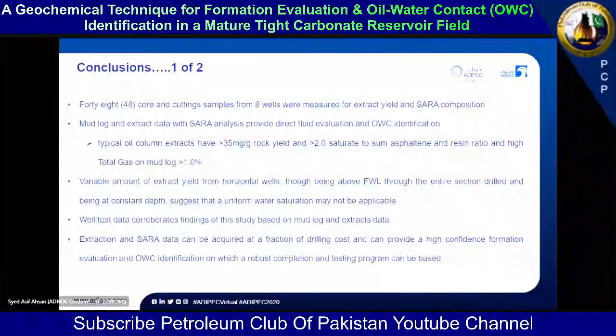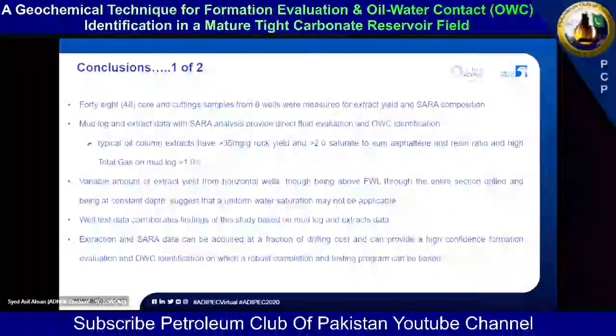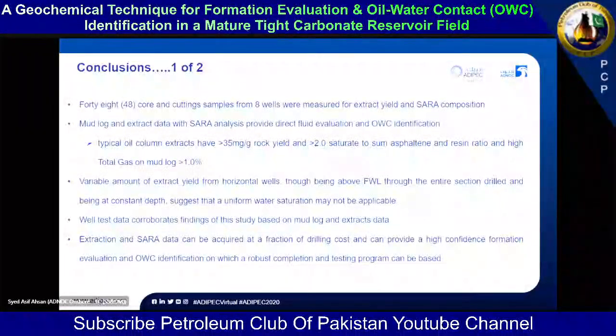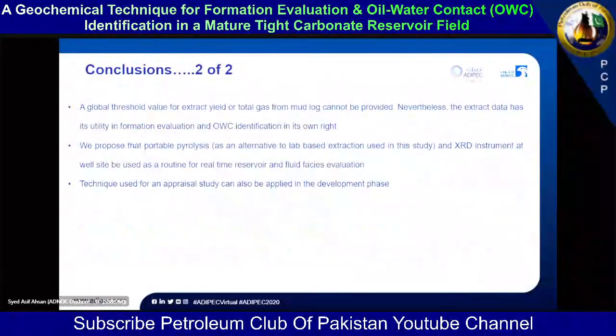Extraction and SARA data and well test data corroborate the findings of this study based on mud log and extract data. So we have plenty of test data which confirms our findings. Extraction and SARA data can be acquired at a fraction of drilling cost and can provide a high confidence formation evaluation and oil water contact identification on which a robust completion and testing program can be based. So a global threshold value for extract yield or total gas from mud log cannot be provided. However, if you have acquired this data in a given well, you can very easily know what you will define as a high value, a low value, and a medium value.